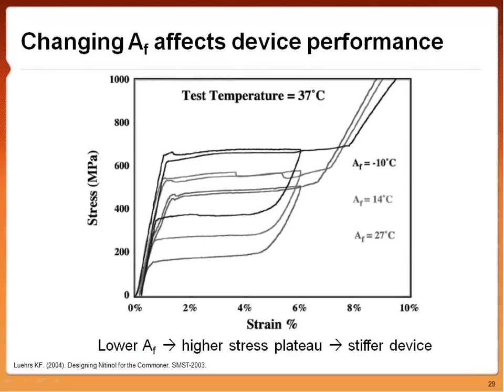And you can see that in these typical flag nitinol curves over here. So the take-home message from this is the lower AF you have, the higher stress plateau you're going to have, which means the stiffer device you're going to have. And that, again, is controlled by the type of alloy you're using and how much nickel is inside your matrix. So again, if we think of these being SE508 material, what really happens for how much nickel we're taking in and out of that parent matrix?